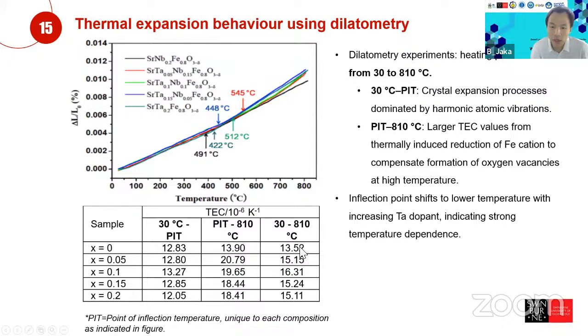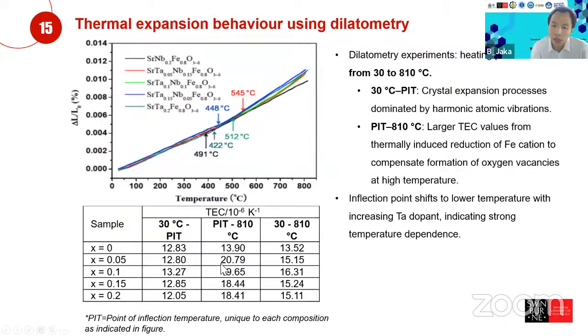Okay, as you can see, when we start adding more of the tantalum, I think tantalum or niobium, I think the X in here corresponds to the tantalum. So as we increase the amount of the tantalum, our thermal expansion coefficient increases as well, meaning that we will have a higher thermal expansion coefficient, because each of the different cations, which are tantalum and niobium, have a different ionic radius.